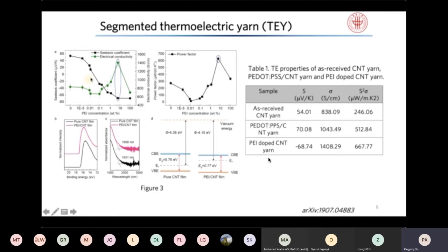We find that the power factor of the pure one is about 240, for the p-type one about 500, and for the PEI one we have 660. This is also the highest one reported. And we confirm the n-type doping by PEI using UPS measurement. We can see that the Fermi level moves upwards, closer to the conduction band edge, and this is a very typical phenomenon for n-type doping. Typically, n-type materials have a very short distance from the Fermi energy to the conduction band edge. And for highly doped n-type materials, you have the Fermi level inside the conduction band.